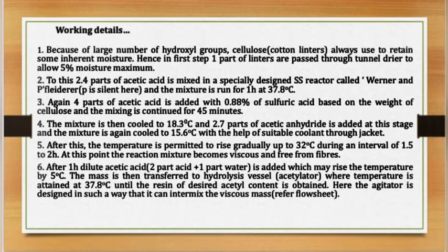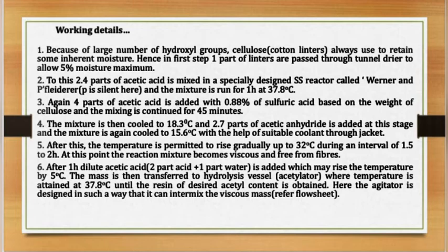Step four: the mixture is then cooled to 18.3 degrees Celsius and 2.7 parts of acetic anhydride is added at this stage. The mixture is again cooled to 15.6 degrees Celsius with the help of a suitable coolant through the jacket. Step five: after this, the temperature is permitted to rise gradually up to 32 degrees Celsius over an interval of 1.5 to 2 hours, at which point the reaction mixture becomes viscous and free from fibers.